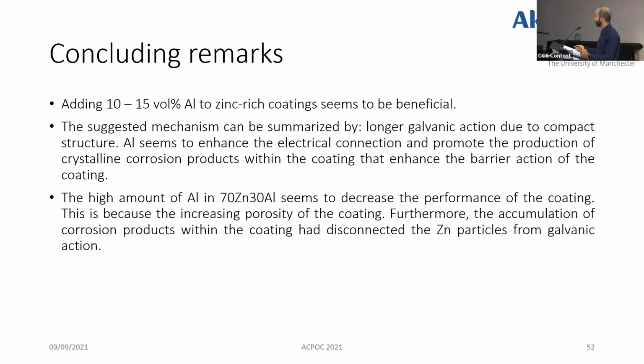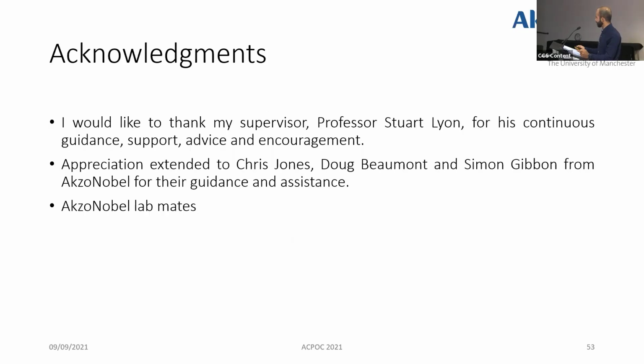And the high amount of aluminum in 70 zinc 30 aluminum seems to decrease the performance due to porosity, and due to the passivity and accumulation of zinc corrosion products at the very beginning of immersion, which prevent the zinc particles from sacrificial action. Finally, I just want to express my thanks to my supervisor, Professor Stuart Lyon, for his